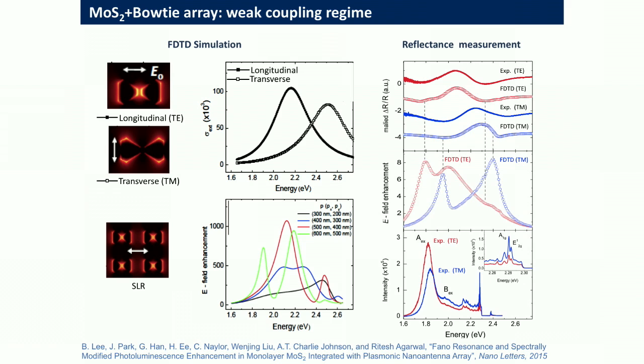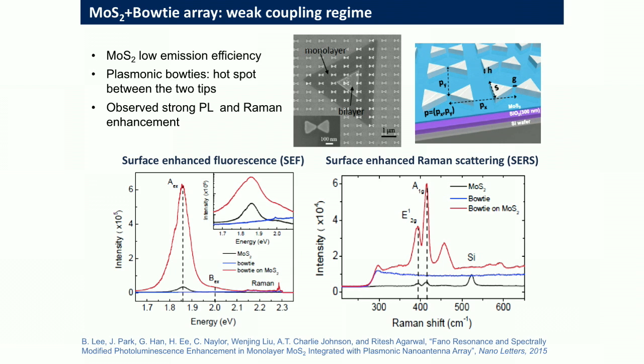So our first experiment was taking this two-dimensional material, MoS2, and patterning a lattice of plasmonic bow ties. With bow ties, you have a very strong mode in between the two triangles, which are very closely spaced apart. And then you have a crystal of these plasmons. By creating this structure, we showed around 100 times enhancement, a Purcell factor of the order of 100, which is very significant for this type of system.